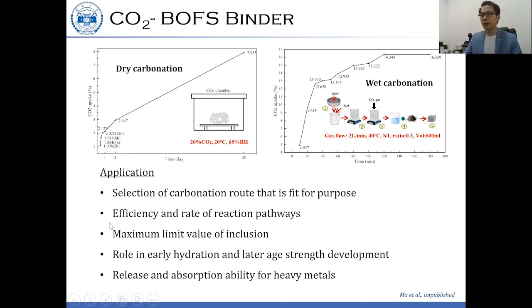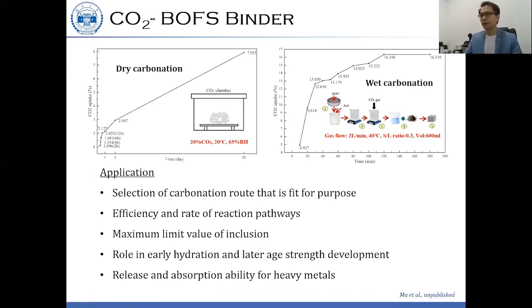It is also very important to understand the efficiency and rate of the reaction pathway for both dry and wet carbonation. Different conditions have different effects on different waste materials. We also have to determine the maximum limit for the inclusion of this active binder in cement or concrete. They contain some calcite or silica gel, so what important roles do these play in the cement matrix? Could they accelerate early hydration, or how do they perform in later-age strength development? With the use of alkaline solid waste for carbonation, we are always more concerned about leaching and the absorption of heavy metals.